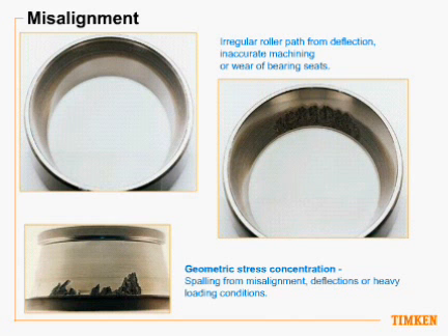When I say somewhere, I mean it could have been on the bearing. You will notice that. It could be on that spacer behind the cone. A lot of times there's like a hardened washer between the outer cone and the adjusting nut. And I've also actually seen the adjusting nut wear, which is bad in the fact that it's putting metal shavings into your assembly. That's not good. And the wear is actually increasing the end play, so that's not good either. Gotcha. Okay.